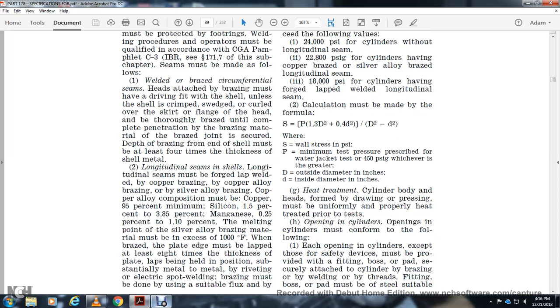Longitudinal seams in shells. Longitudinal seams must be forge lap welded, or copper brazed, copper alloy brazed, or silver alloy brazed. Copper alloy composition must be copper 95% minimum, silicon 1.5% to 3.85%, manganese 0.25% to 1.10%. The melting point of silver alloy brazing material must be in excess of 1,000 degrees Fahrenheit when brazed.